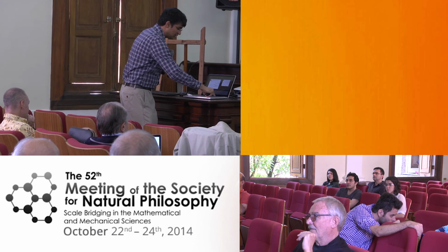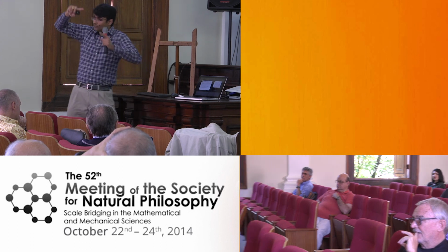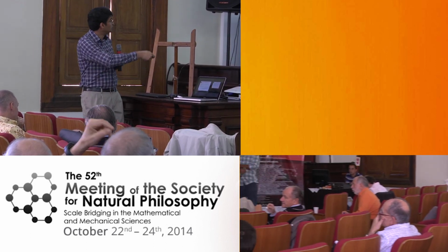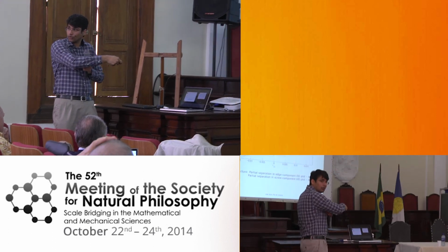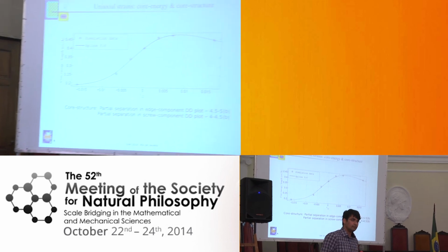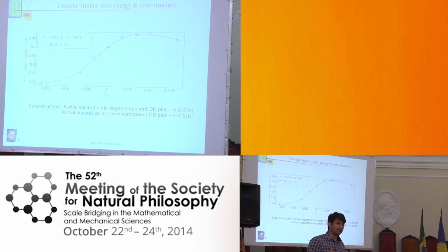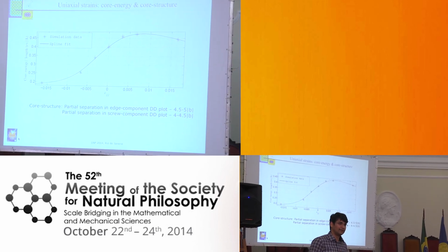So all these plots include how the interior core changes when we apply the macroscopic deformation. For instance, the partial separation distance in the edge component changes from 4.5 to 5 Burgers vectors. Maybe I'm not answering your question, but...